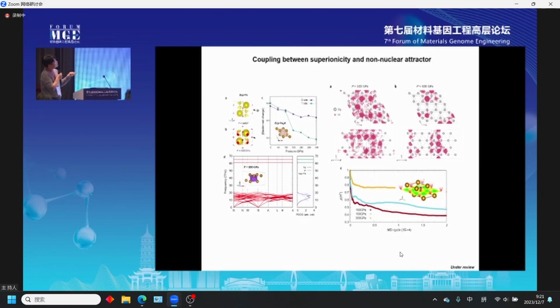So this is the MD simulation we did, and these red dots, this trajectory, show hydrogen diffusion at low pressure. It mostly stays at this electride site, which is a non-nuclear attractor site, and with increasing pressure it stays much longer. So this is a summary at 100, 150 and 300 gigapascal: the normalized time the hydrogen stays at the non-nuclear attractor electride site during the MD simulation.